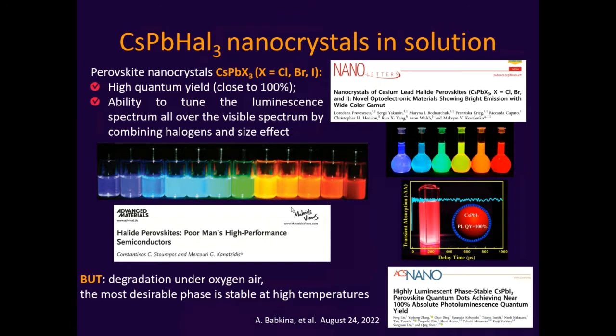So since 2014, there are a lot of papers concerning these nanocrystals inside of the solution. And yes, they do have very high quantum yield. If we are talking about bromide crystals, they have luminescence in the green region. If we are talking about iodine, they have it in red, and chloride crystals have luminescence in the blue region. So we have a perfectly ideal RGB with a very high quantum yield. But the problem with these nanocrystals inside of the solution is that they are not stable.